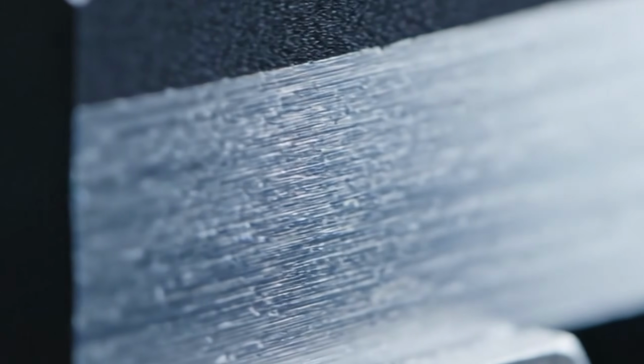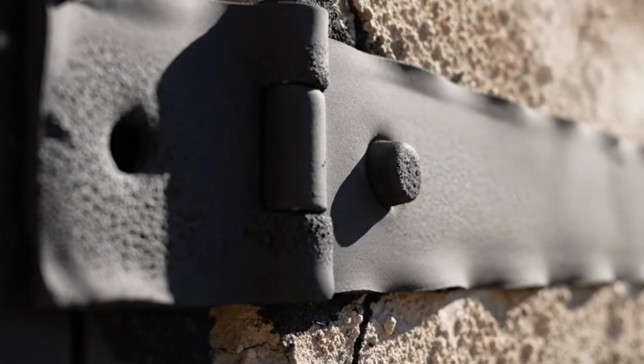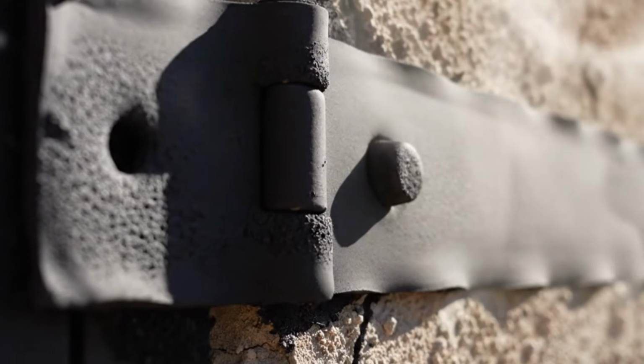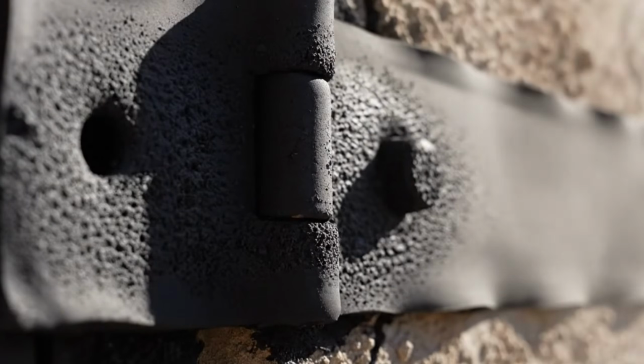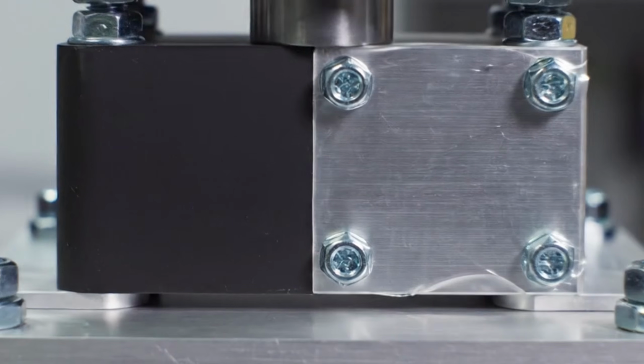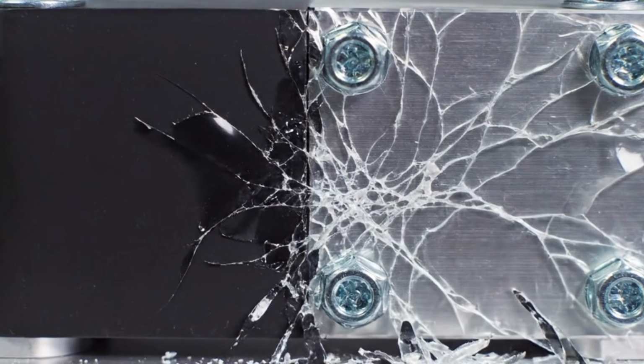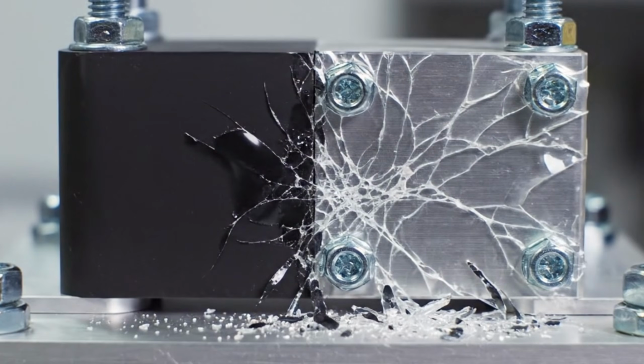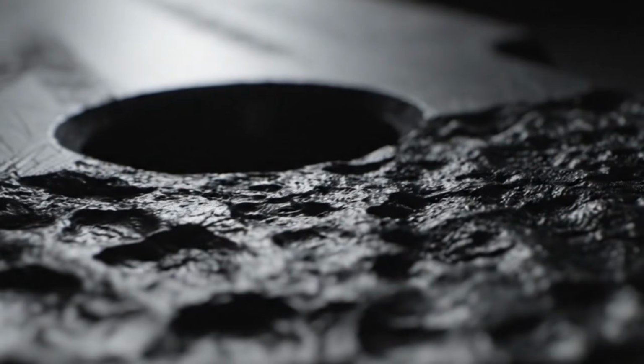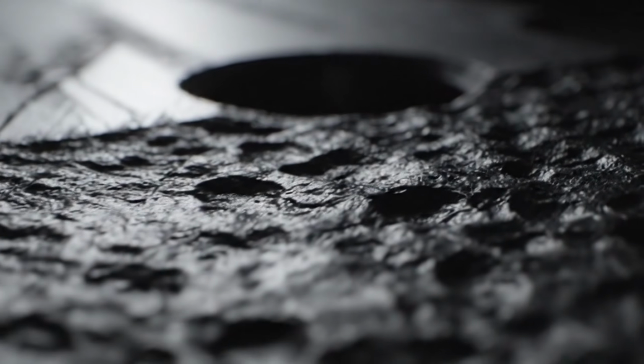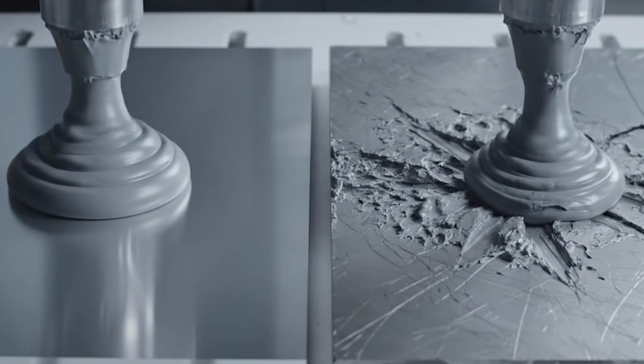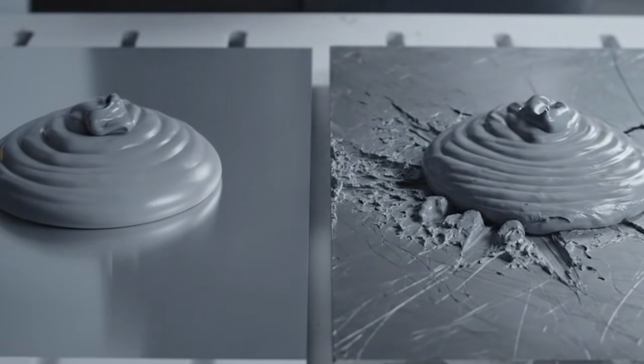The fifth advantage is sacrificial weathering. People often imagine a good coating should remain visually unchanged forever. But many old protective layers were designed to take damage at the outer surface while preserving what mattered below. Sunlight, dust, abrasion, and rain slowly degraded the paste itself first. That outer loss was acceptable because the coating could be renewed cheaply. The metal lasted because the paste suffered in its place.